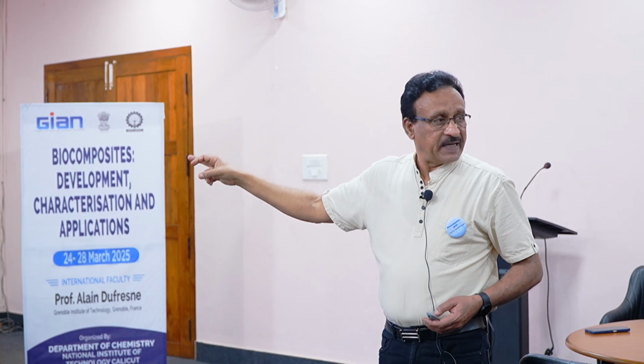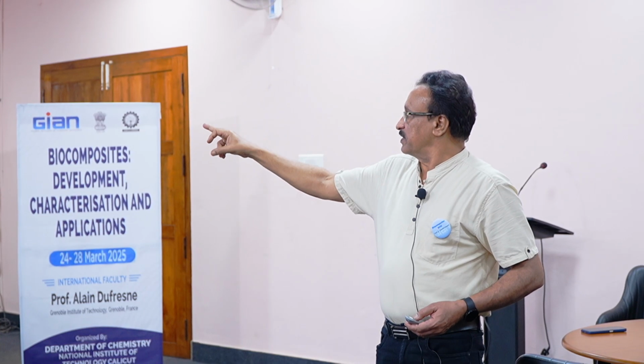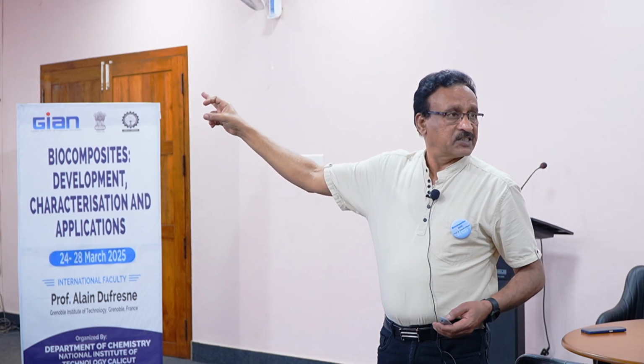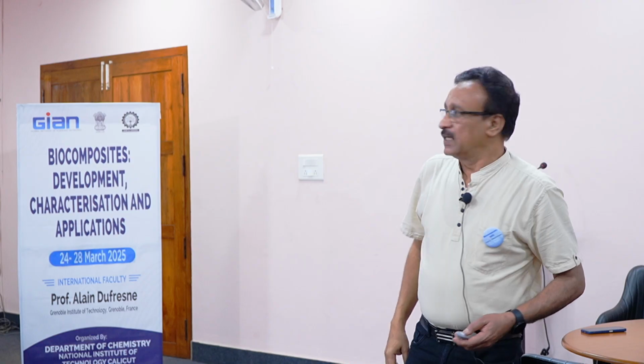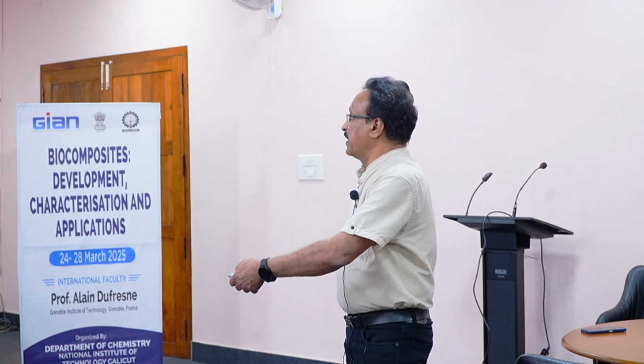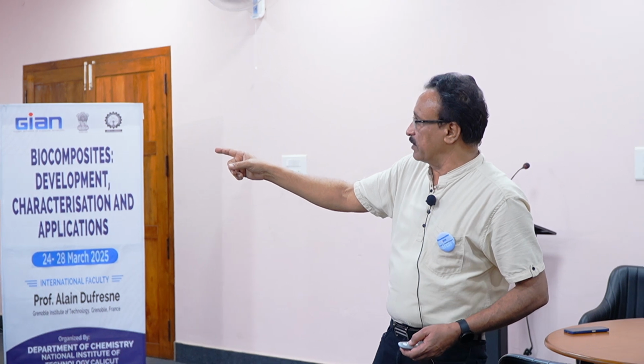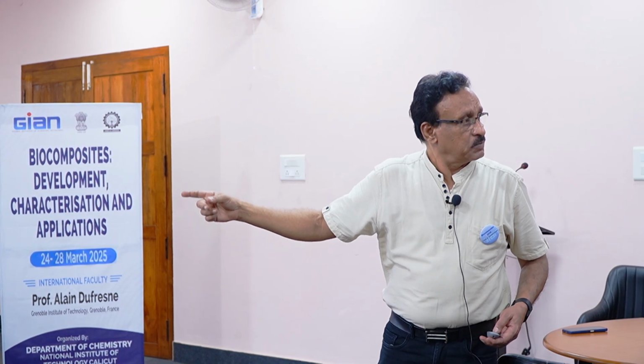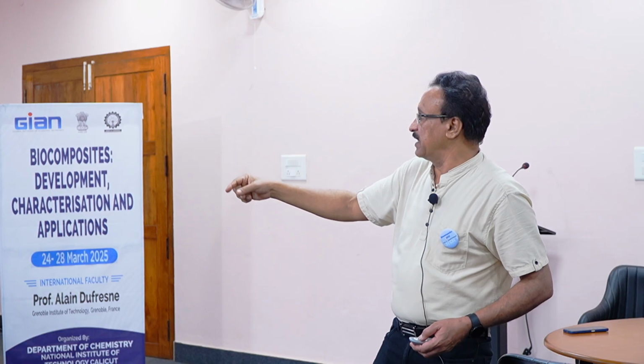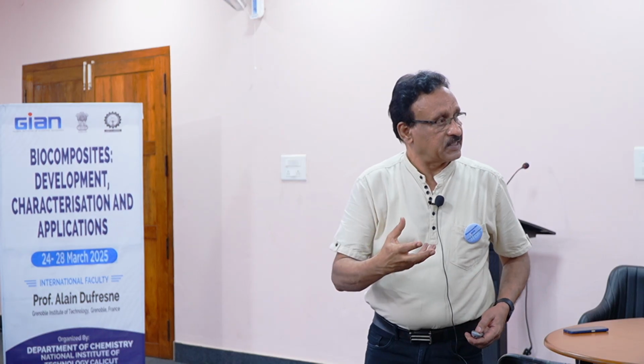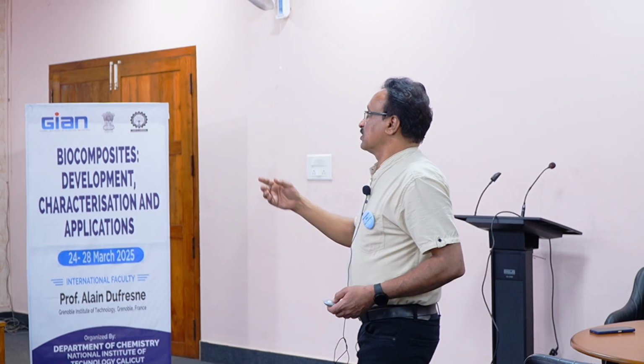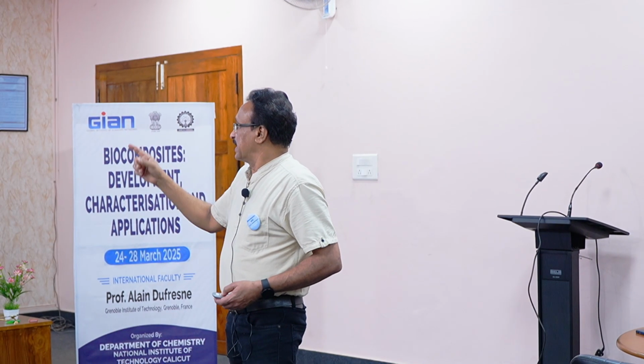So she has made a cartoon based on that, which is on the right-hand side, showing PLA alone, gelatin alone. When they are combined, the P10 system, at the right-hand side top, has a uniform morphology. Based on that, we defined a system. Using the usual protocols, there are other standard techniques to find out the porosity. The porosity has been found for the P10 system. It contains 75% pores within the system. So that's a good indication for us.